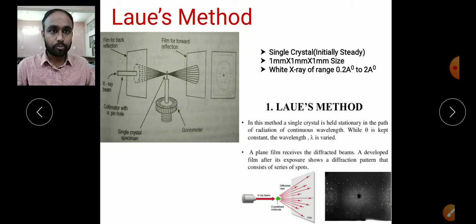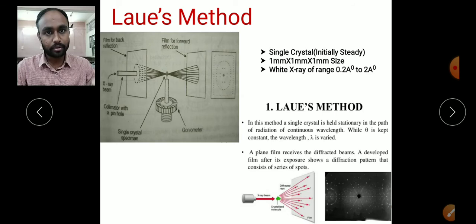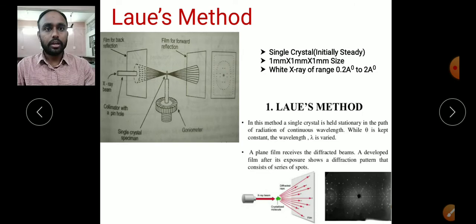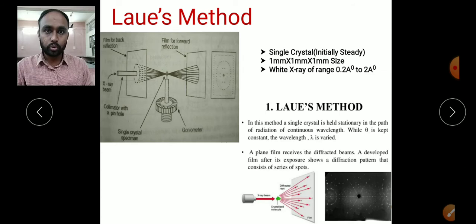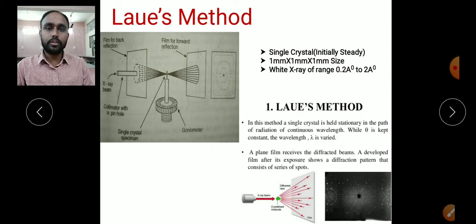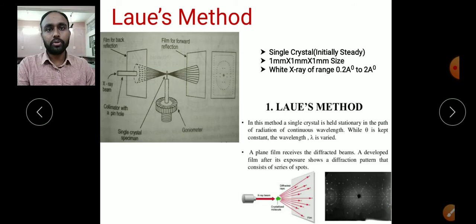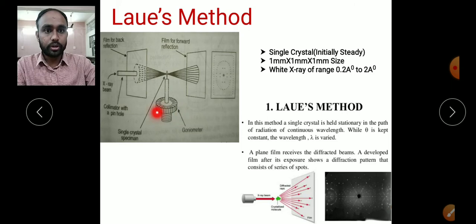If the rays are out of phase we get a dark point. The bright points on the film represent constructive interference from scattered atoms. For a particular plane, we get one set of points. Then we slowly rotate the goniometer so that each side of the crystal gets illuminated by the incident X-ray. By rotating, all planes of the single crystal are covered by the X-rays, and all the resulting points come from the whole crystal, not just a single plane.